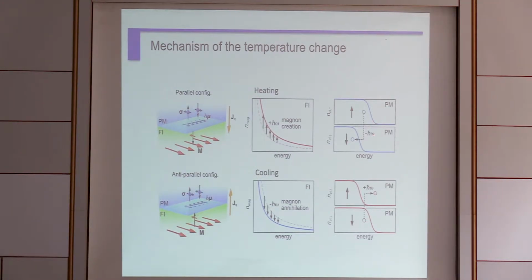When this kind of spin accumulation is formed in the conductor layer, the predominant scattering is like this, from upspin to downspin. Because of the angular momentum conservation, this means the magnon number should be enhanced. And this frequency change is handed to the magnon frequency change. So this means the magnon sector is heated and the metal sector should be cooled down.